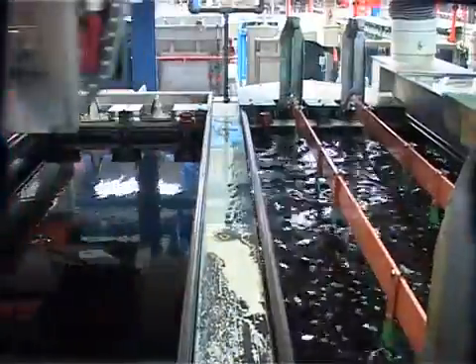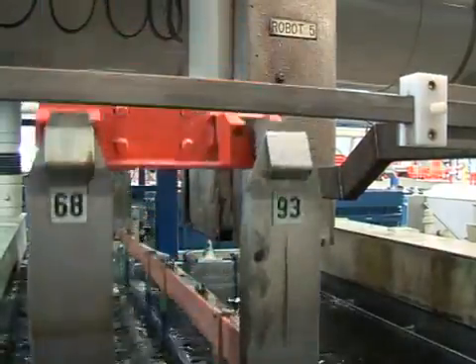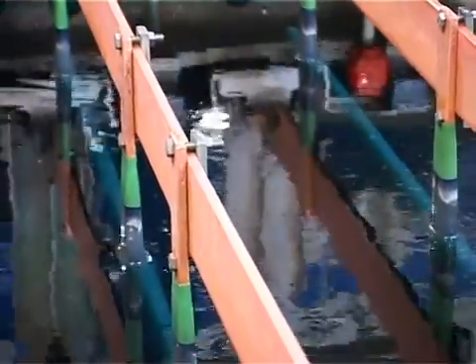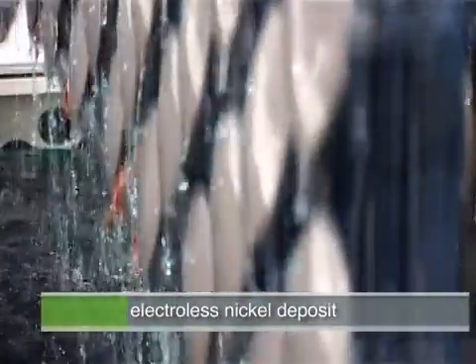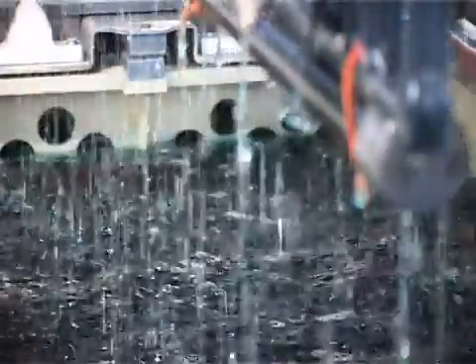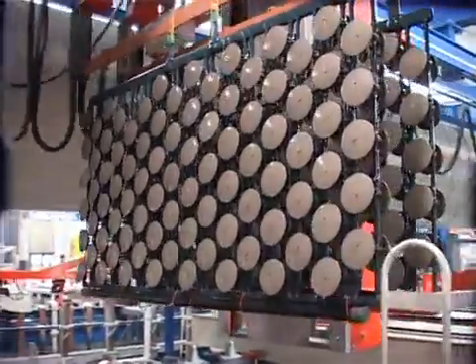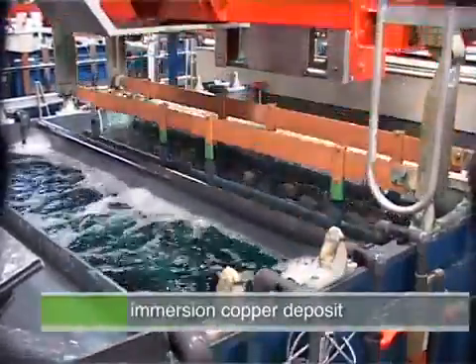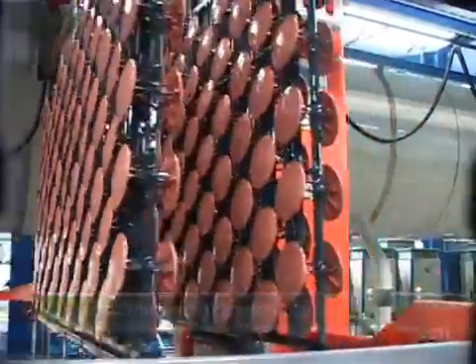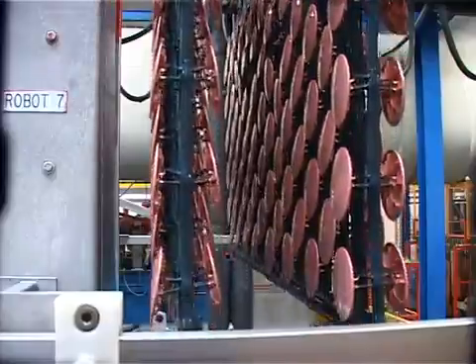After acceleration, the surface is ready for a thin layer of a conductive metal to deposit on the palladium catalyzed surface. This occurs from an electroless nickel process step, which deposits a thin, dense nickel-phosphorus alloy. The nickel alloy layer thickness deposited from the electroless nickel ranges from 0.2 to 0.4 microns, resulting in the plastic parts becoming conductive, which is very important for the deposition of the copper, nickel, and chromium electroplating sequence. After creating the initial conductive layer with the electroless nickel, racks of parts are processed through an immersion copper or nickel solution to further improve their conductivity.